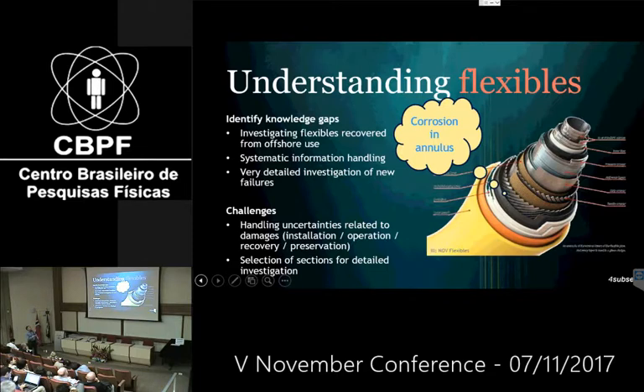There are a lot of challenges in this one. Just handling things related to a damage is a serious difficulty. Then installation, operation, recovery, and preservation. Very often you find that it's difficult to distinguish between what has happened as a result of the recovery or what has been the failure. It might take a long time before you get into a position of having the possibility to do a dissection. And then very often you find that the section which has failed or has a challenge is a long section. You don't know very much about it. Where to start, and you cannot always do examination of kilometers. So there are several challenges related to this.